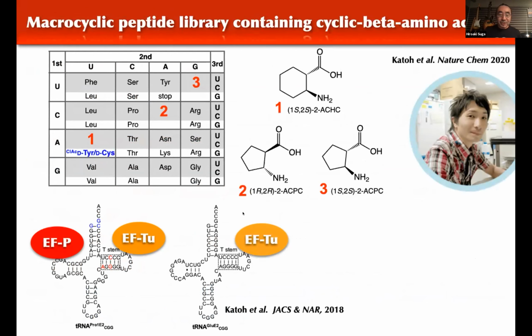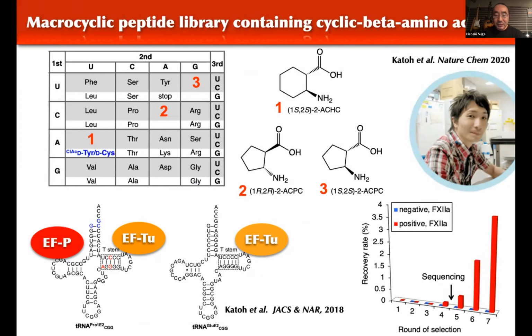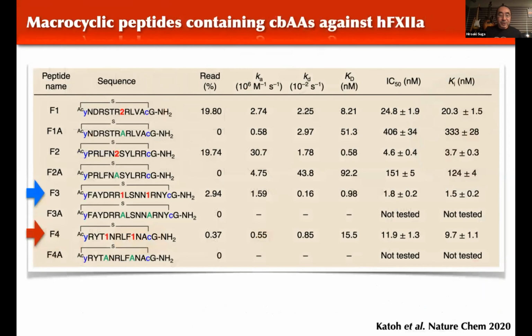These amino acids were notoriously unable to be put into the library before, but after many experiments, thanks to the efforts of Dr. Kato, who made a new tRNA, we can place these molecules into the genetic code. Then we tested peptide selection against one of the drug targets, called factor 12A protease. And we found molecules that very strongly bind to the target, in the picomolar range.